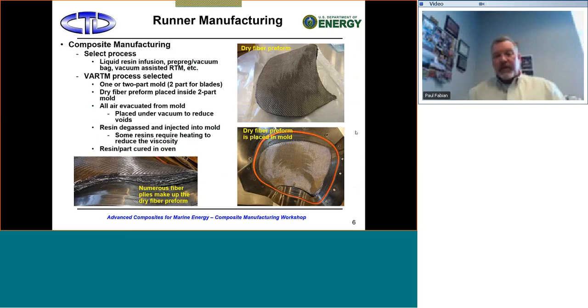So moving on into the actual manufacturing, and the big step here is deciding which process to use. There's a lot of different methods of fabricating a composite. Liquid resin infusion, pre-preg vacuum bag, that's the primary process that aerospace uses. But there's also what they call vacuum-assisted resin transfer molding, or VARTM, and that was the process that we selected. And what that means is you are using either a 1- or 2-part mold, depending on what surface finish you need. You might only need one side that has a controlled surface. In some cases, like for us, we wanted both surfaces controlled, so we used a 2-part mold.